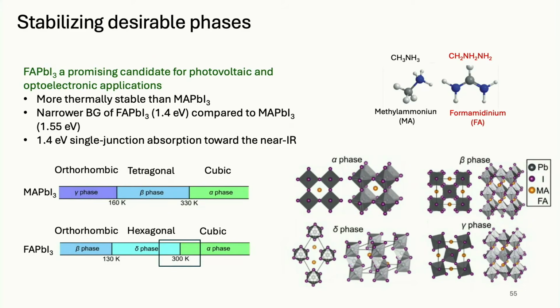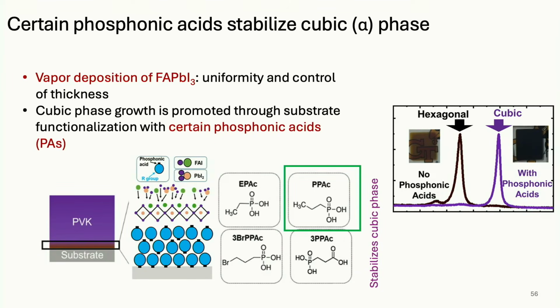But we don't give up so easily. My friends noted that if you grow formamidinium lead iodide in the presence of a phosphonic acid, then you can make the cubic perovskite. Here, this is like an X-ray diffraction, that if you have the phosphonic acid, you get the cubic phase. If you don't have it, you get this other delta phase. A phosphonic acid just means a phosphorus with, you see, a double bond O and 2 hydroxyls. So this is the phosphonic acid group. And these all have abbreviations. This is ethyl phosphonic acid, propyl phosphonic acid, and so on.